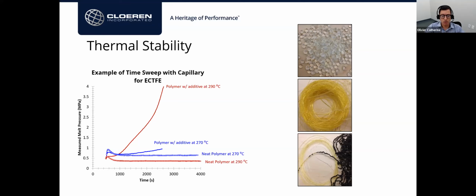So the die was performing fine with the neat polymer, but then they were observing a lot of degrading materials very quickly when they were using additives. I still don't know today what the additive is. I can tell you that after the fact, we did the same time sweep experiments, measuring pressure over time, and the additive had seemingly a strong effect on pressure, and we could see that the material is starting to degrade at 270 degrees C, and at 290, the degradation was dramatic.